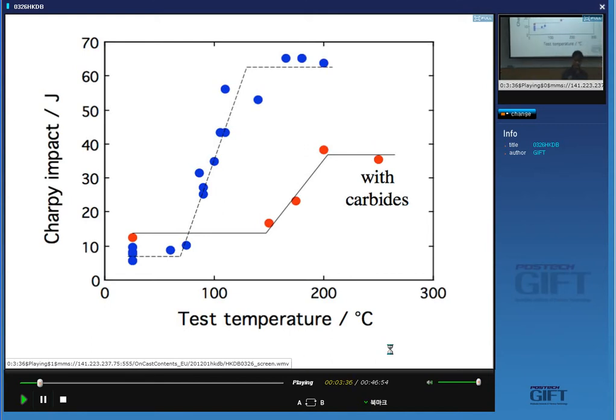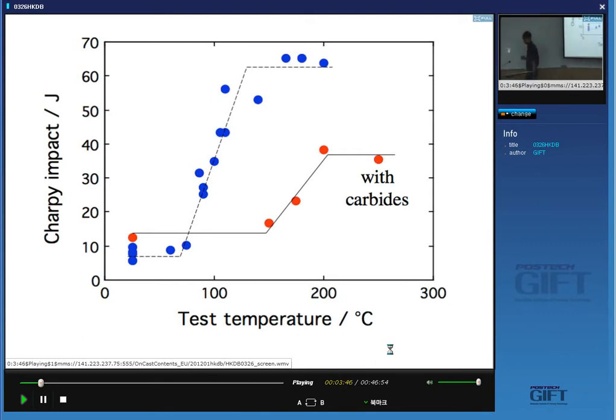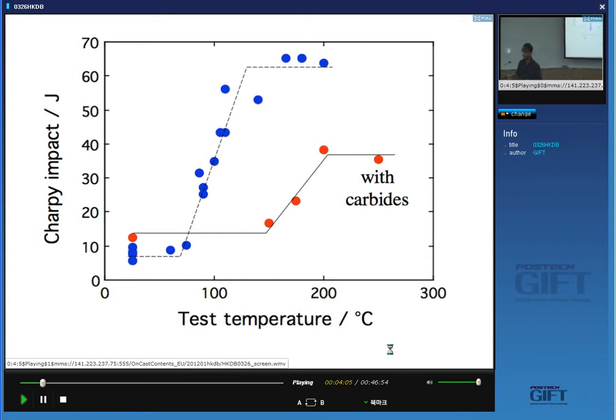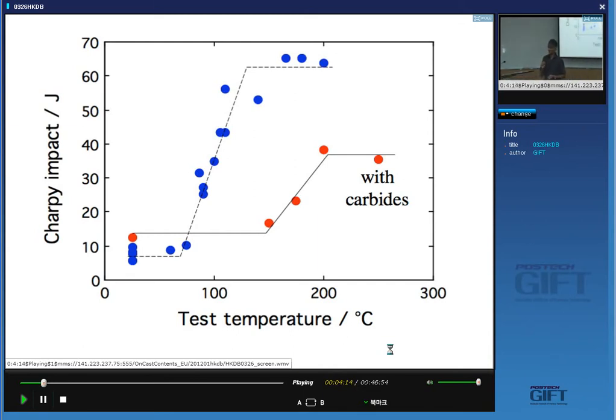If you reduce the carbon concentration to less than 0.05 weight percent, then the carbides will be fine and are not the initiating sites for fracture. So how can we stop these carbides from precipitating? Titanium will capture the carbon and form titanium carbides, which are cubic in shape and coarse because they form at a very high temperature — so we don't want that either.